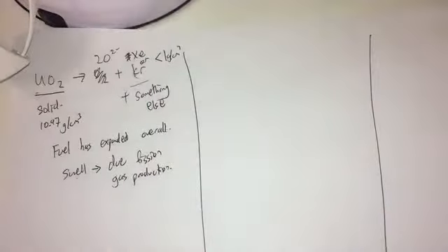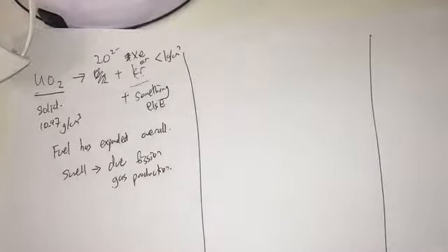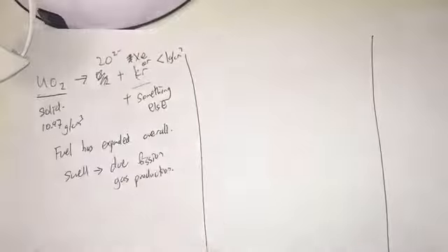So it can be krypton or xenon here, but the effect is more or less the same. These gases will exert pressure on the fuel pellet and cause it to expand. So creation of such species tends to decrease the thermal conductivity of the fuel, since when the uranium is gone, it's replaced by a gas which has rather poor thermal conductivity.